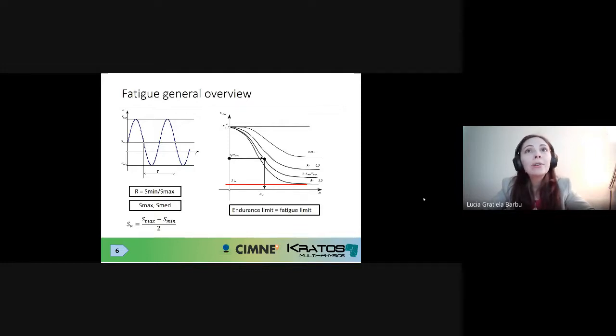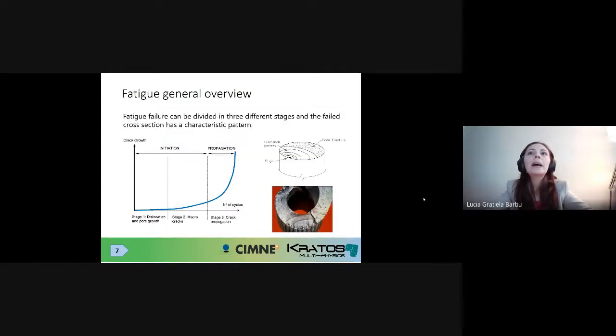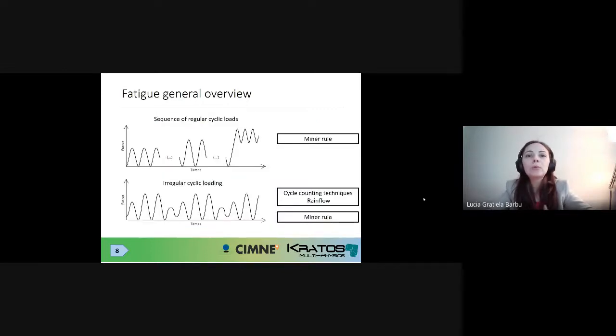This is why all the different formulations for high cycle fatigue developed throughout the research start to have a lot of importance, and the industry is starting to be very interested in this. Okay, now, regarding the failure due to fatigue, there is a characteristic pattern when you see a fatigue failure surface. Basically, fatigue initiates at an origin, which is generally found close to a defect in the internal structure of the material. It can be a large pore, it can be an inclusion, etc. Then you have an area of propagation of the crack which initiated at that defect, where you can see a clamshell pattern. And in the end, when the crack has propagated through the cross-section until it is reduced to such a small level that it can no longer bear the load, then you have a final fracture, which is quite brittle. Now, another concept that is important to establish at the beginning.